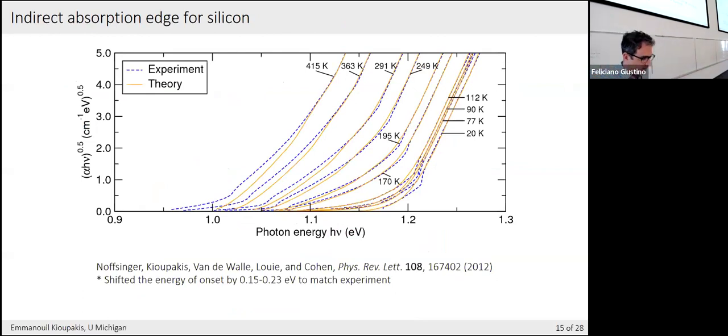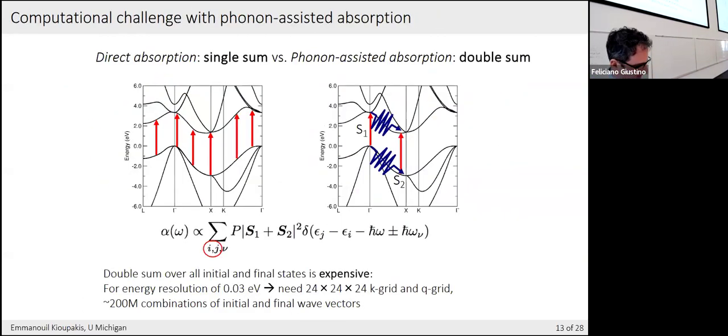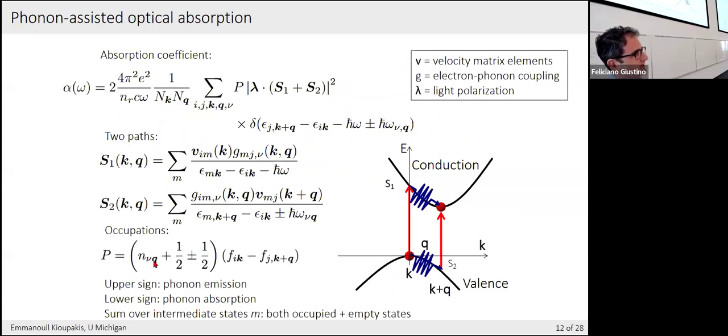Great question. So temperature has many effects, as we'll hear about in this school. In our case, the temperature we put in comes through the phonon occupation numbers, right? This is the one that we took into account for that calculation. High temperature, more phonons, strong electron-phonon coupling. However, temperature has many other effects, including lattice expansion. Crystals expand, so you need a new lattice constant. In the case of silicon and ceramics in general, that is not a very big factor. For metals, it is. For insulators, not so much, or ceramic materials.